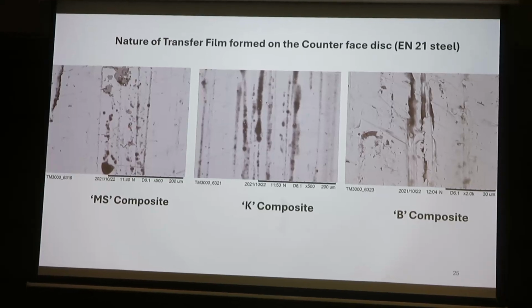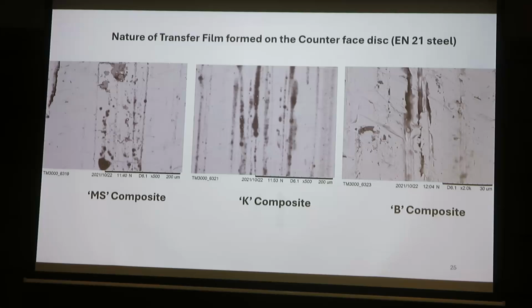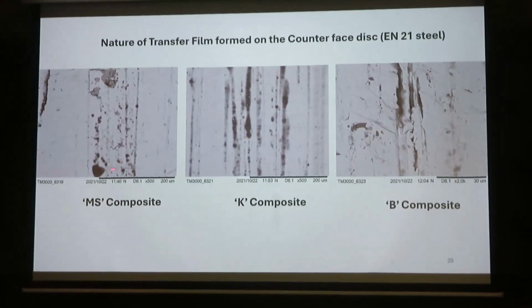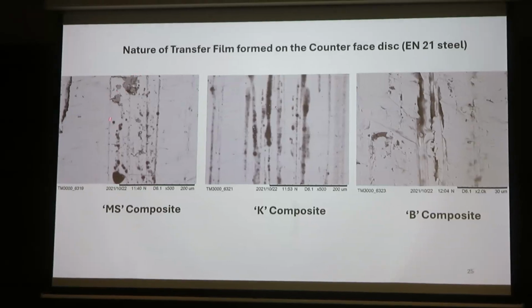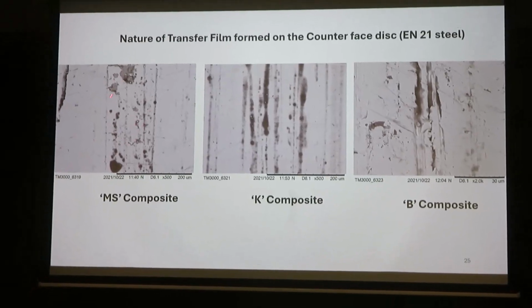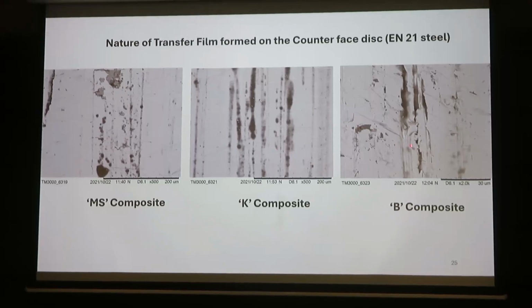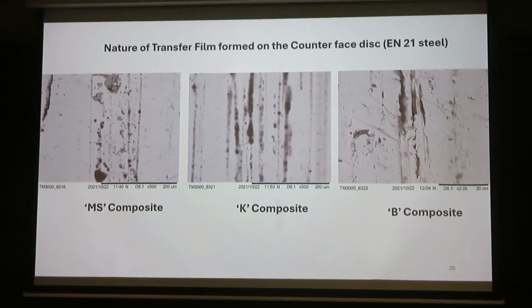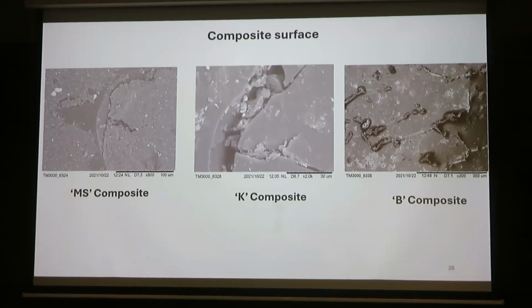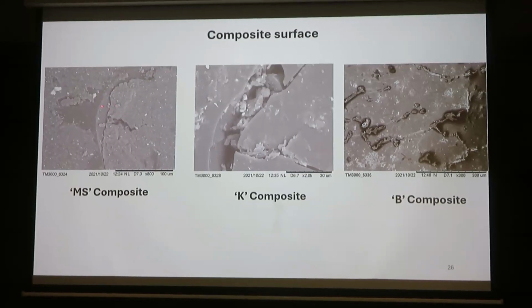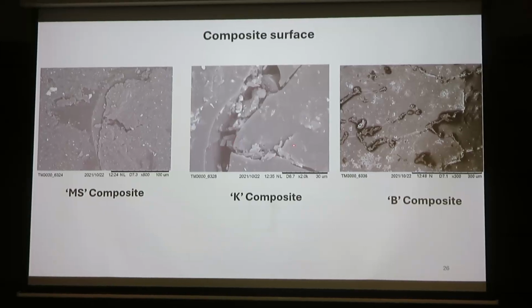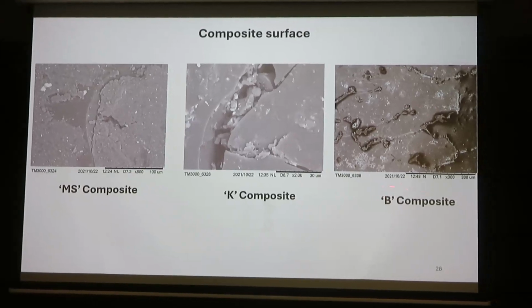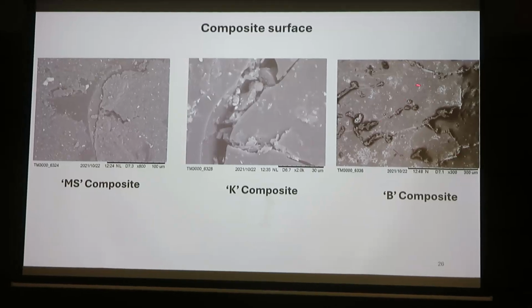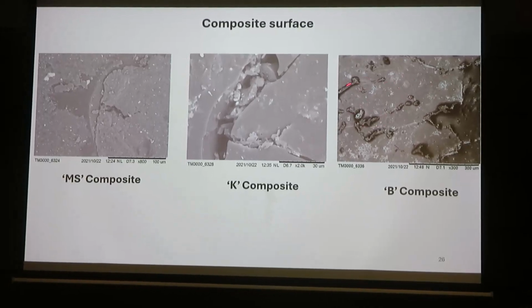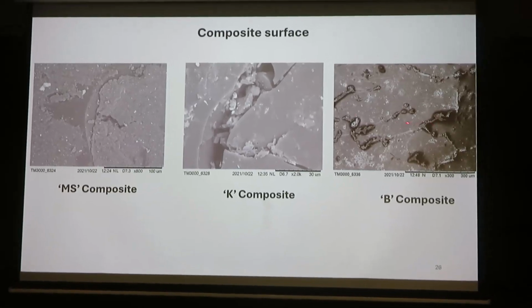Here also we saw the transfer film. As we know, polymers and polymer composites in general form transfer films, and the MS base composite here is slightly thicker than for the Kevlar and for the one with oil. And on the surface of the composite we could see some cracks happening. So these are some of the cracks, whereas for the base oil composite, where we added liquid oil, we did not see so many cracks, but there is the presence of oil on the surface.